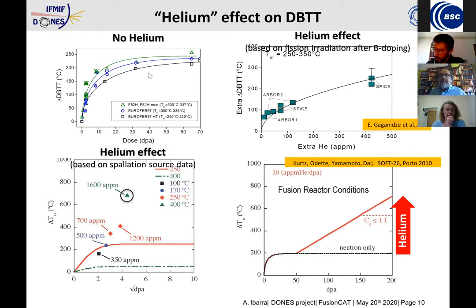There are some experiments that have been developed over time in which we try to guess what the helium effect will be. You can see here two examples of the helium effect. The first one is based on experiments in which we impurify the steel with boron, and with this we generate a lot of helium inside the material due to nuclear reactions. The other experiment is based on results coming from a spallation source that has a very different neutron spectrum, but it also generates a lot of helium in the material.